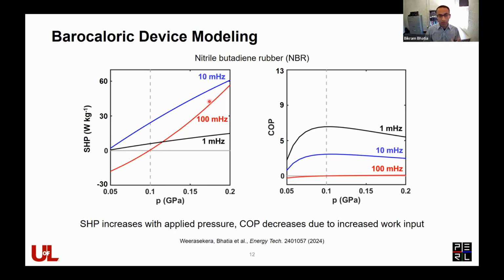You see that if you go to really high frequencies, the specific heating power starts to drop, and that's because at these relatively high frequencies, you don't have enough time for heat exchange between the solid media, the barocaloric media, which has relatively low thermal conductivity, and whatever heat transfer medium you have outside. So we were using a heat transfer coefficient of around 100 watt per meter square Kelvin for this model.